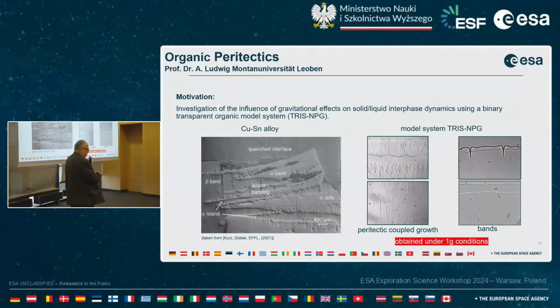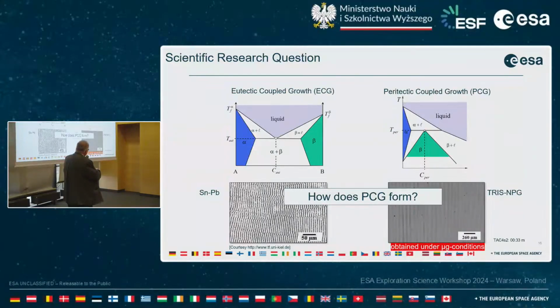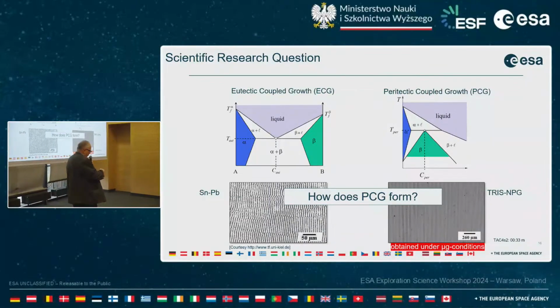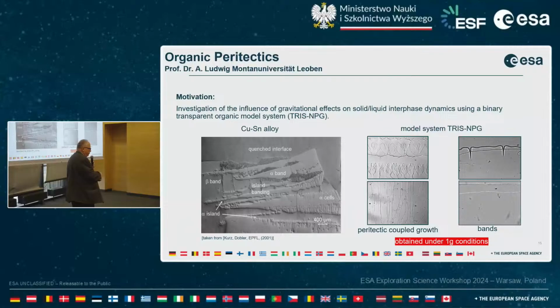You can see, yeah. But if you compare this here, this is, let me say, peritectic coupled growth. This is a mixture of peritectic coupled growth and bands. And this is what we found out in space. So there's a clear difference. Without going more into scientific details, I believe this is the effect of the convection in front of the solid-liquid interface, that it gets smaller, larger, smaller, larger.